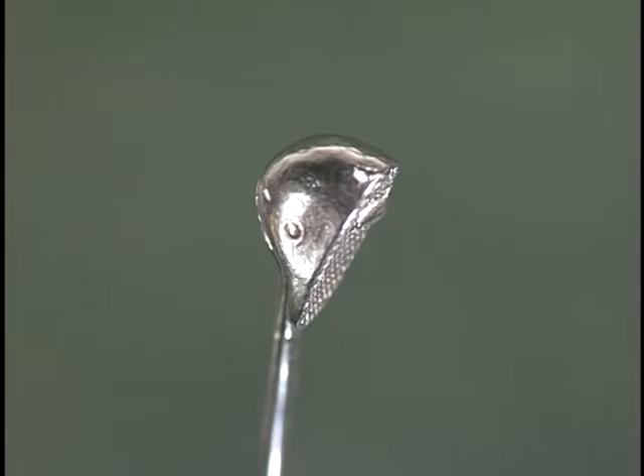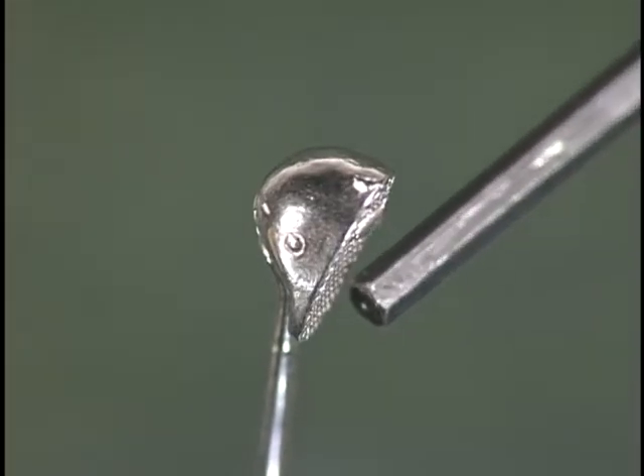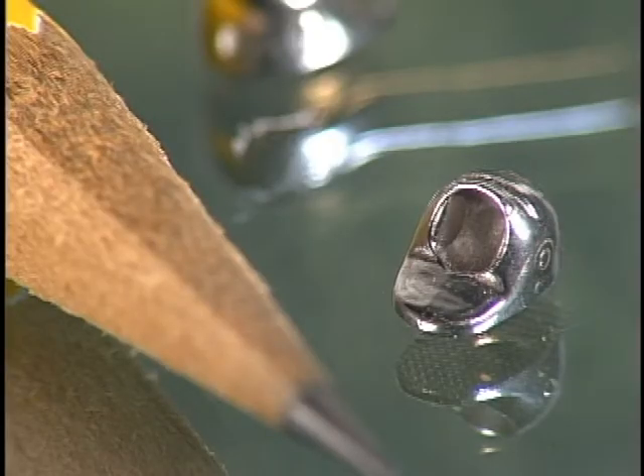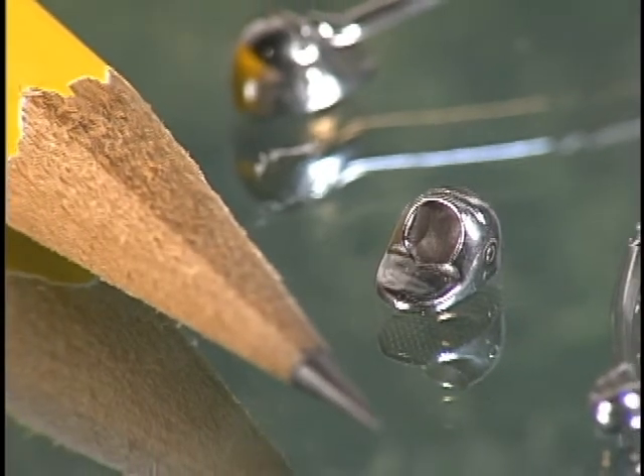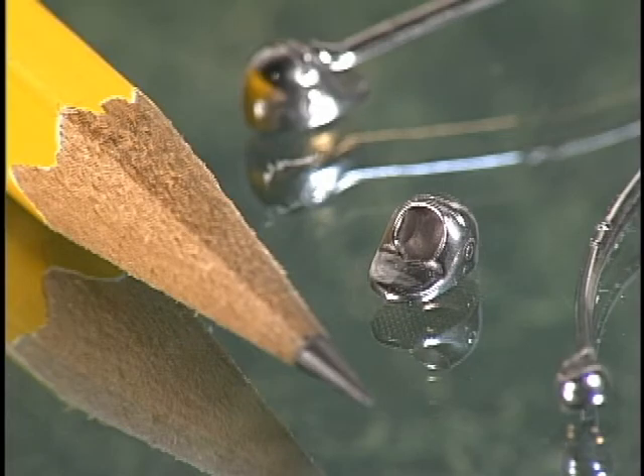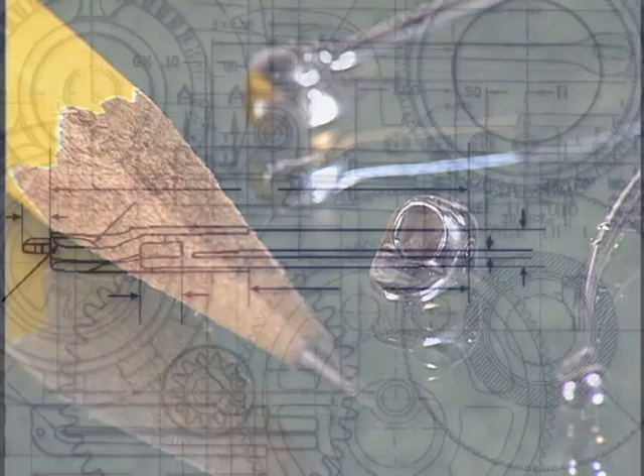Made from a nickel-free stainless steel, the parts are formed to a density of 7.6 grams per cubic centimeter. They exhibit a yield strength of 80,120 psi, an ultimate tensile strength of 95,520 psi, and a 22% elongation. Metal injection molding offered considerable cost savings and higher yield than competing manufacturing techniques such as investment casting.